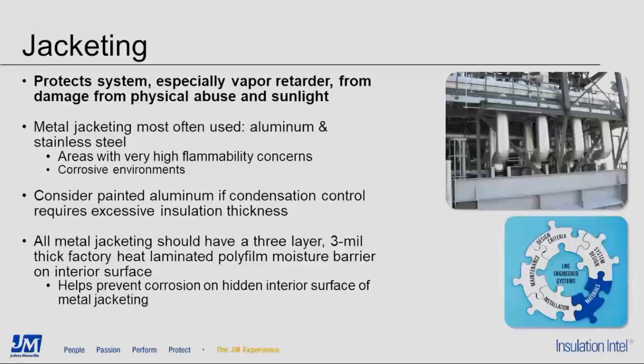In addition, Jim talked about the thickness of the insulation, that a relative humidity of 88% and above causes the thickness to significantly increase. One way, if you're running out of room, to cut down on the thickness of the insulation is to consider using painted aluminum, like a white, to help control condensation in those applications.